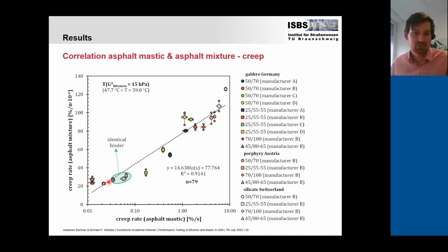Then finally, also for the high temperature range, which means here we looked at temperatures 47 to 59. So softer binders were tested at lower temperatures, harder binders were tested at higher temperatures in order to see the significance of the binder stiffness. Here we see creep rate on the x-axis from the DSR and creep rate on the mixture from the cyclic compression test on the y-axis. Actually, you see here the x-axis is displayed in logarithmic scale, since we found that the mastic differentiation is much bigger than the mixture. So you can see here the polymer modified binders, which are here the 45, 80, 65, for example, but also the 25, 55, 55 here.